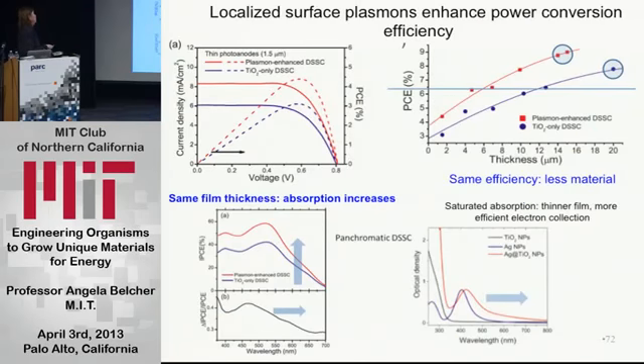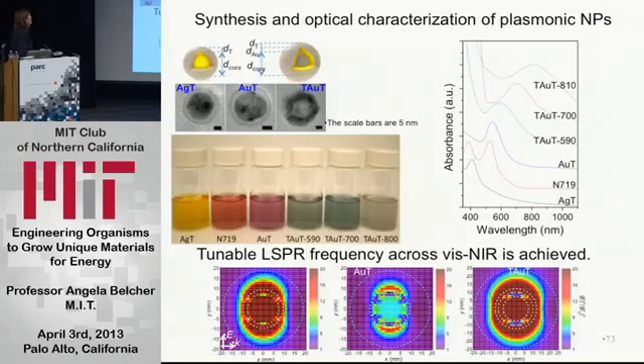And we were able to do that by making silver, I think this was a silver nanoparticle, with titania over it. In this case, we have really thin photoanodes of 1.5 micron, and this is basically with our nanoparticles and without our nanoparticles, and so we see a bump in here. You can actually look, in this case, we have the same efficiency but less materials using our plasmonics. Then we started looking at what we call panchromatic solar cells, which is actually broadening the absorption wavelength by adding these materials. And we did some really fun things by growing either silver nanoparticles or gold nanoparticles or core shells of these, and started to be able to tune the wavelength based on adding these.